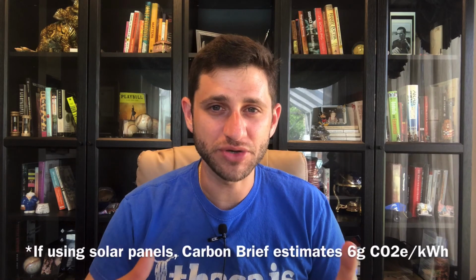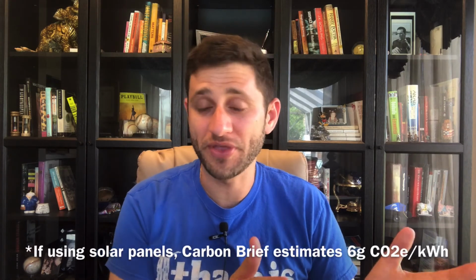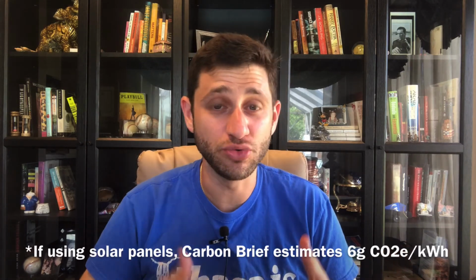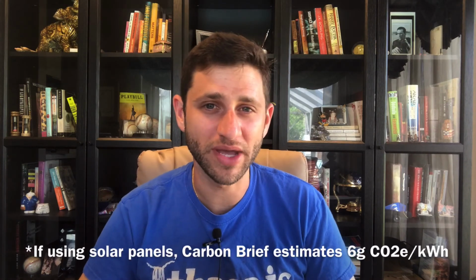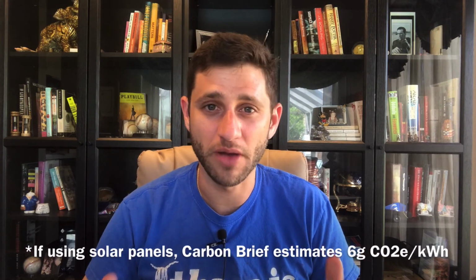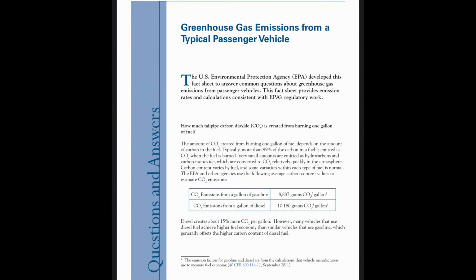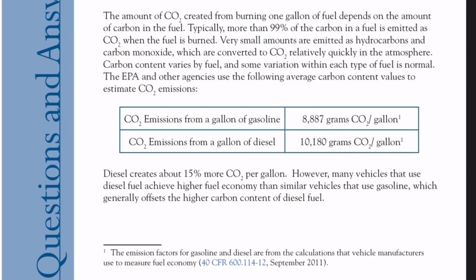So now that we understand where the energy is coming from, both to manufacture the lithium-ion batteries and to run these batteries based on power we're drawing from the grid, how does that compare to exhaust from internal combustion engines? Now, national averages are provided by the EPA. We can see that for every gallon of conventional gasoline, it produces 8.8 kilograms of CO2 per gallon versus diesel at 10.2 kilograms CO2 per gallon. And we see that, yes, diesel does produce more CO2 per gallon, but tends to give you some benefit in terms of miles per gallon equivalence, so sometimes that can offset.